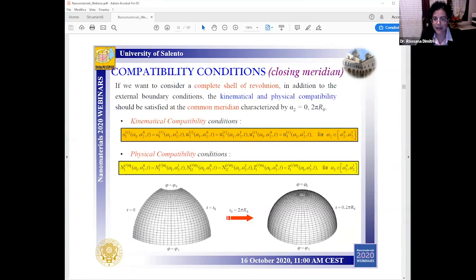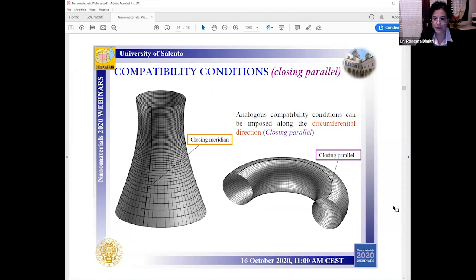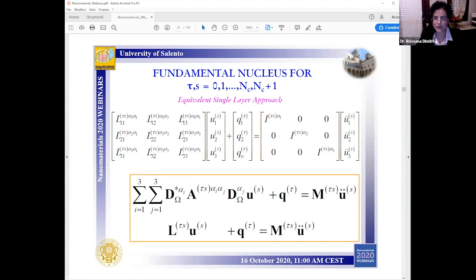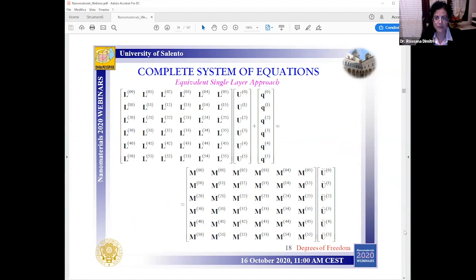And at the same time, if we want to treat a complete shell of revolution as a structural member, we have to satisfy the kinematical and physical compatibility conditions at the common meridian, characterized by fixed values of alpha 2, as you can see here in this slide, since the shell of revolution represents a special case of a panel of revolution, maintaining the problem completely two-dimensional. And look at these two further examples of shells of revolution, just to show you that similar compatibility conditions can be enforced along the so-called closing parallel or closing meridian. And then we can write the fundamental nucleus in terms of the displacement field defined along the reference surface. And then we can assemble the complete system of equations, as you can see here.